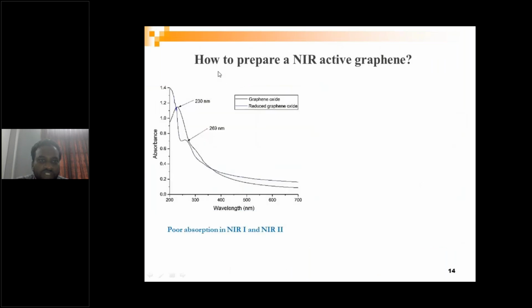Wow. So when you look at the UV-visible NIR spectra of graphene materials like graphene oxide, or graphene, or reduced graphene, you see it has very good absorption in the UV region, but less absorption in the visible and NIR. So a lot of research has been demonstrated using bare graphene oxide and reduced graphene. So it has less absorption.